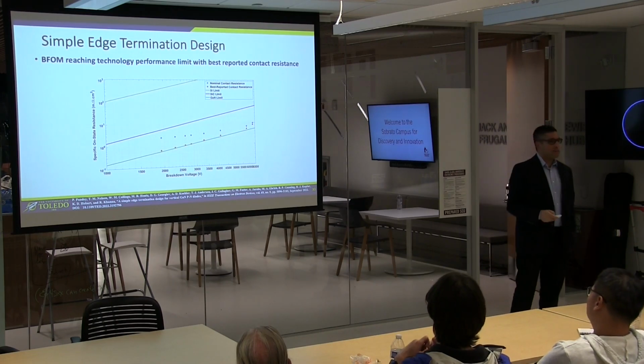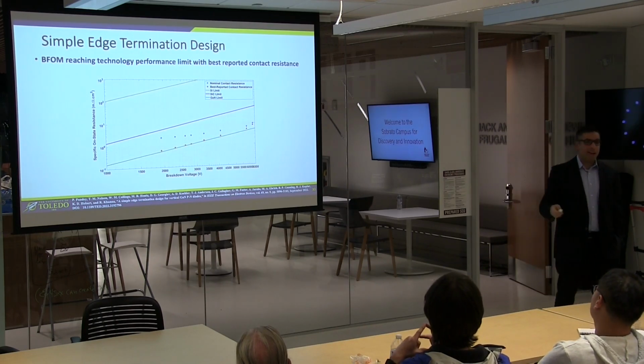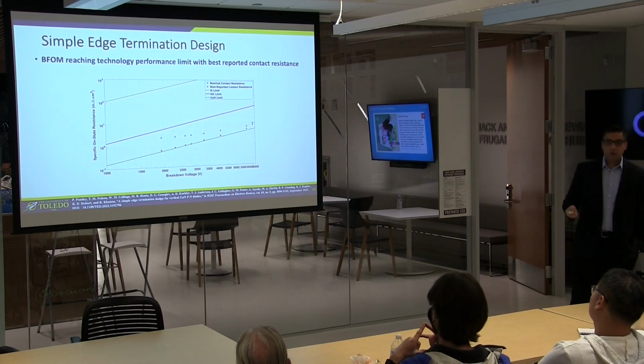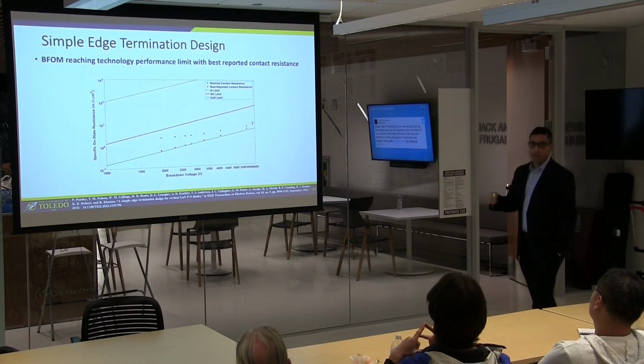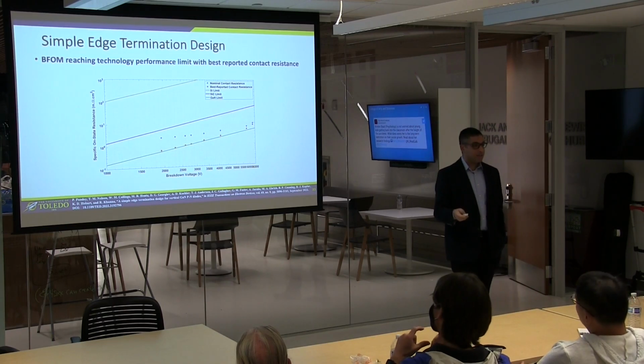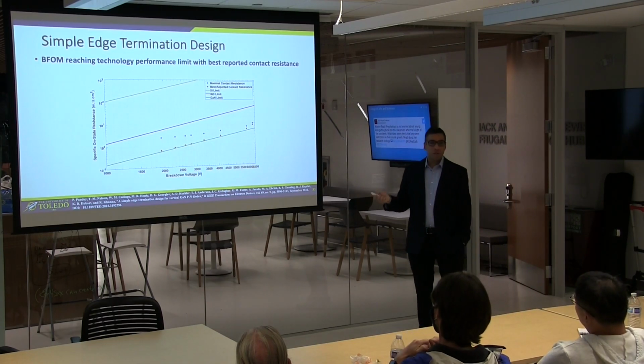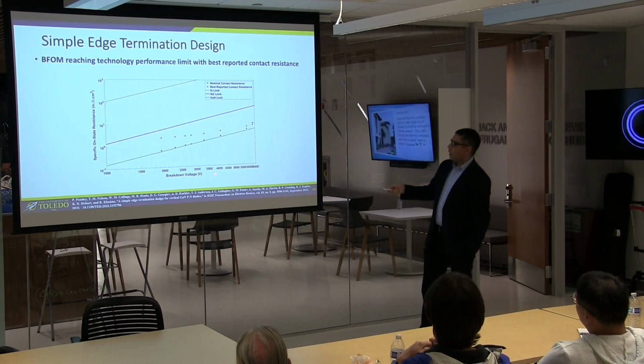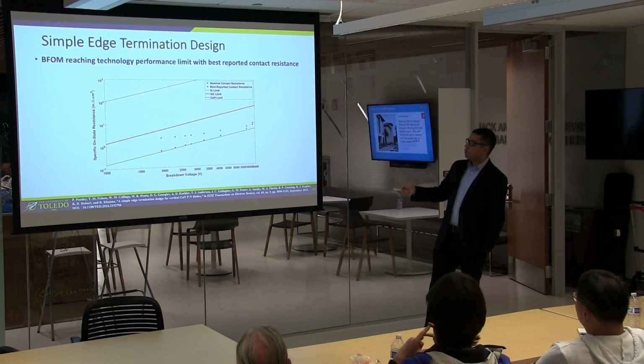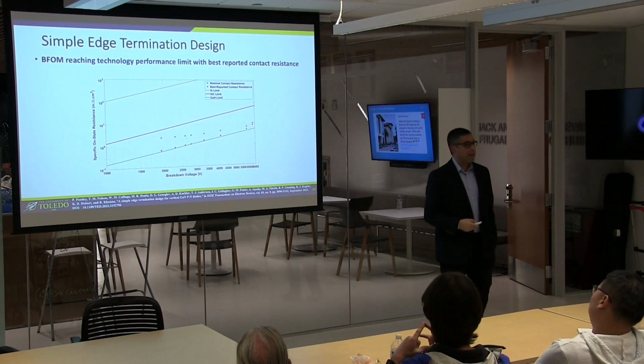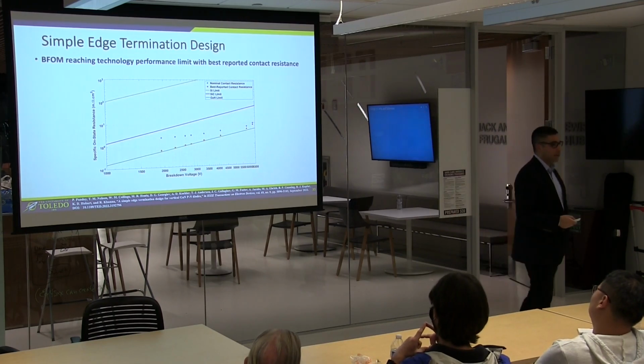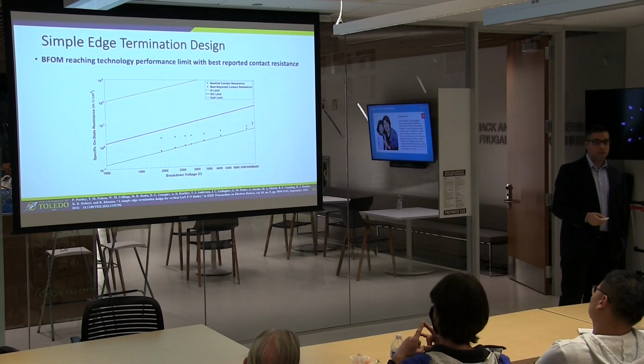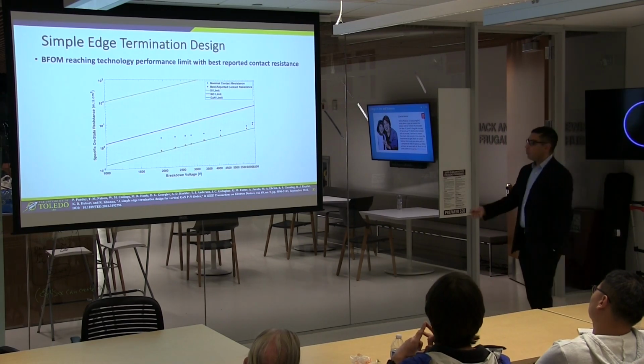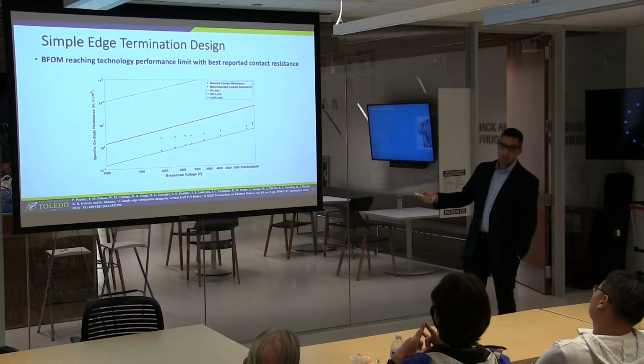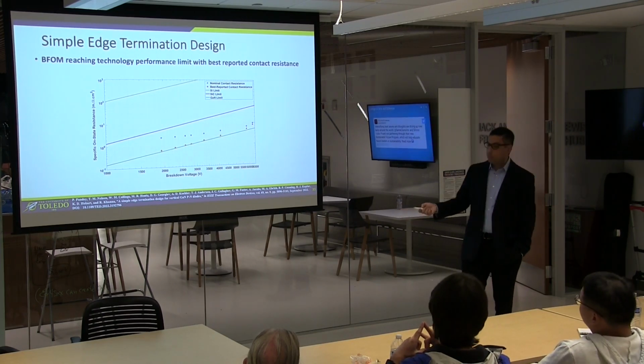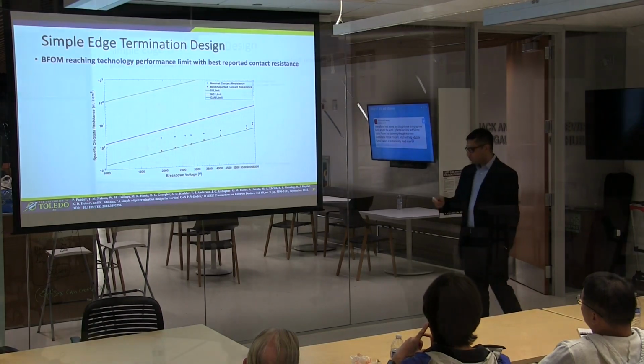Now, the contact resistance that we're using both in simulation and at NRL is not the best. So what do we do when we take the best reported contact resistance from the literature, swap out the ones that we have in our simulation? Then we get the orange data points. So we're really showing that we're basically landing on the theoretical limit of GaN with this type of structure, once we use the best contact resistance. We use the ones that we have right now with these blue dots, just swap those out in simulation with the best reported ones. Now you're pushing the theoretical limit.